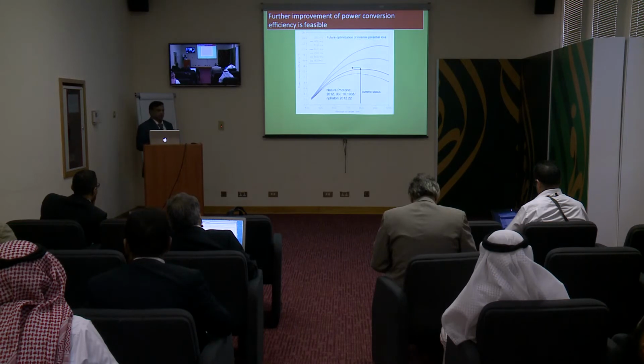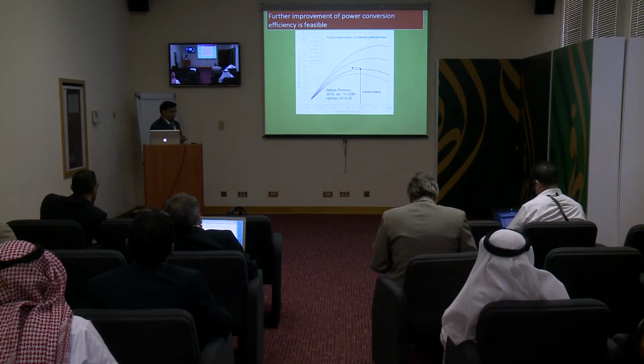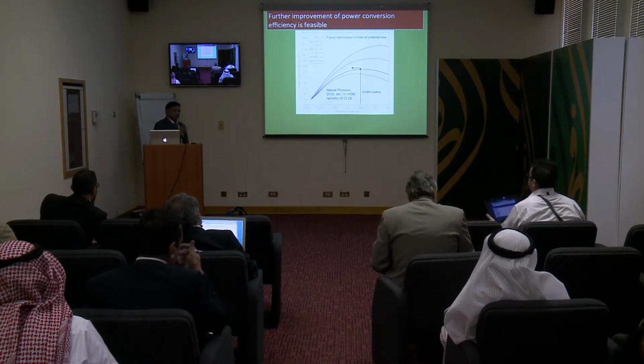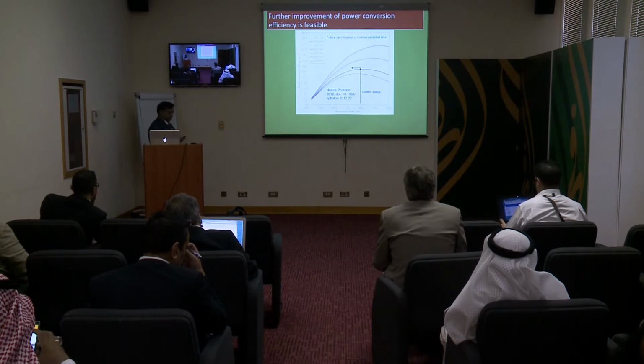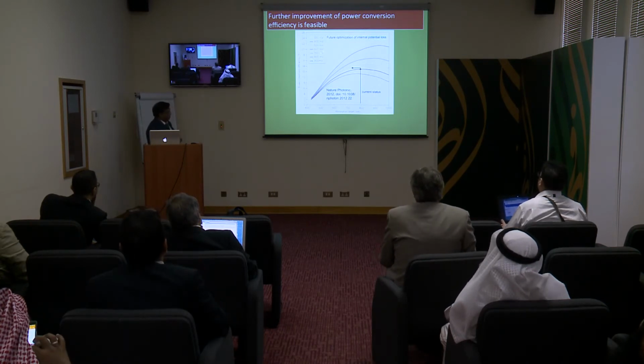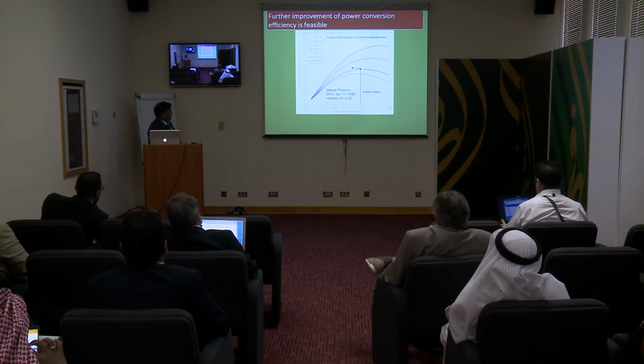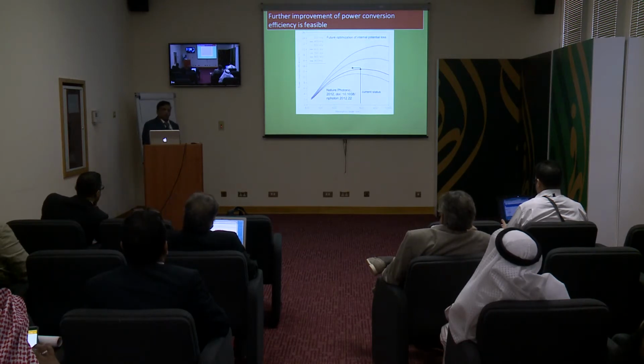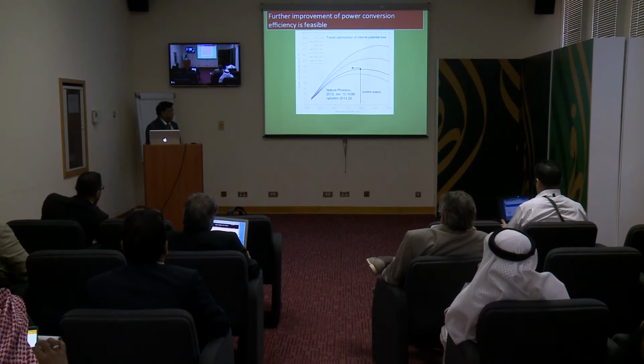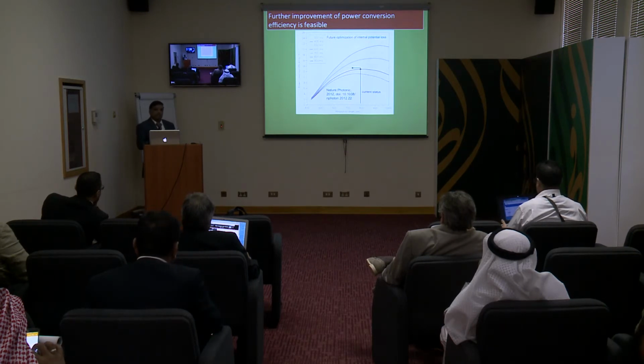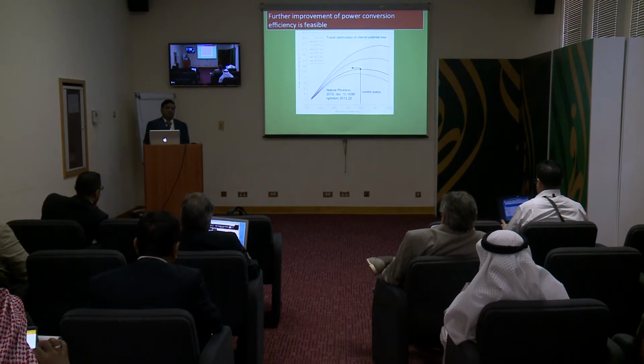That is the overpotential which we are using, because you cannot tune the redox potential of the iodide electrolyte. That is the loss which we lose in the open circuit potential, because the open circuit potential is the energy difference between the Fermi level and the energy of the electrolyte. So if you go on decreasing the loss along with the spectral response, it means you can increase the performance of the devices proportionally. The direction you can see in this figure is that one can tune the spectral response to the red. At the same time, one has to reduce the gap between this HOMO level and the energy of the redox electrolyte. That can be possible only with an alternate redox couple.